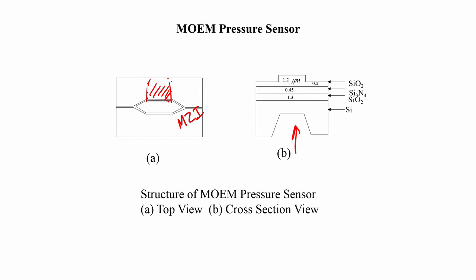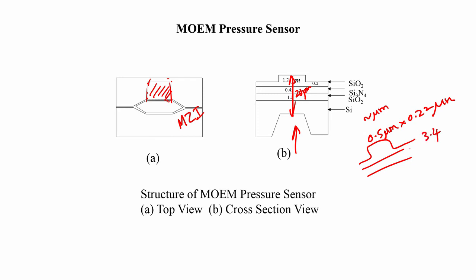Typical thickness, consisting of the waveguide etc., could be of the order of a few microns, 20 microns, and waveguide dimensions, as you know, in silicon will be of the order of a fraction of a micron or half a micron. Typical dimension is 0.5 micron by 0.22 micron. These are typical dimensions of an optical waveguide. And large refractive index is another important property of silicon, of the order of 3.4. Oxides, of course, you can oxidize the silicon and you have a refractive index of the order of 1.49 or so. So, these are typical parameters of the